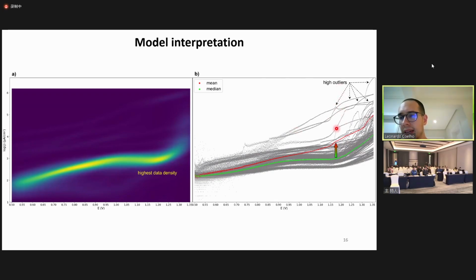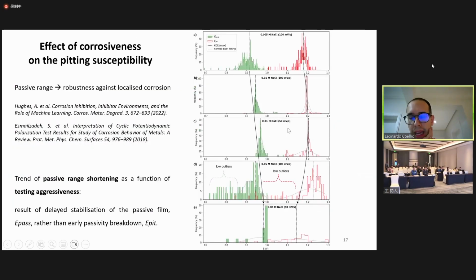And again, these high outliers are cases where we have particularly active sites on the surface, leading to very, very active pits on the surface. And here I show we should always try to plot histograms, right? We could not escape from it.